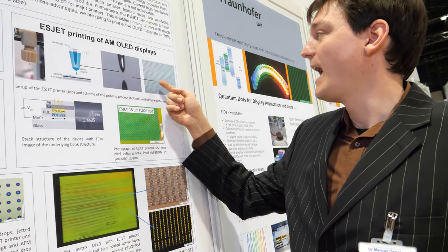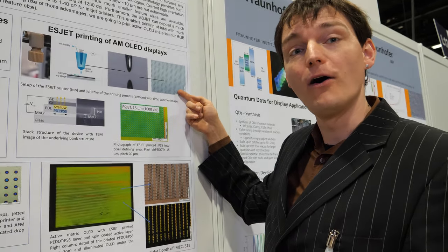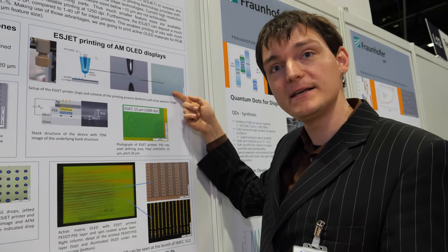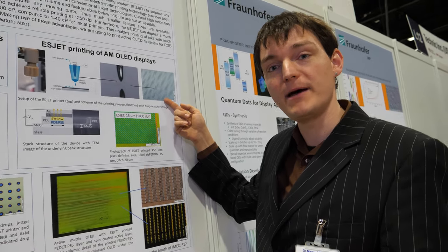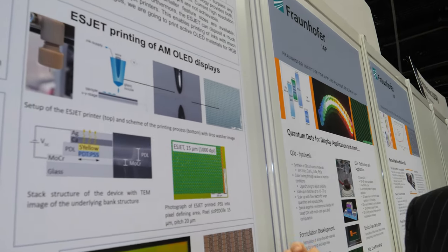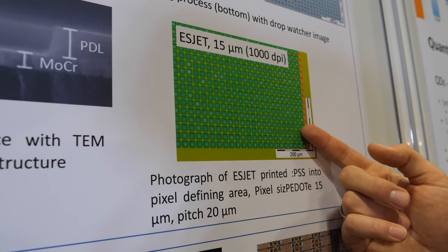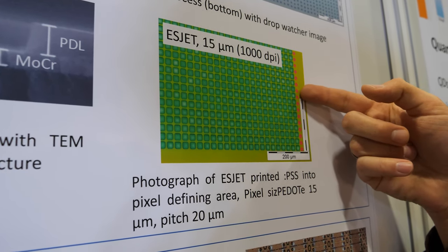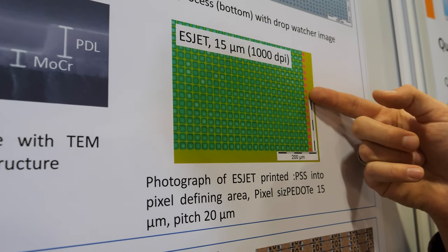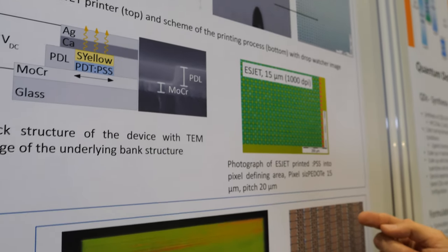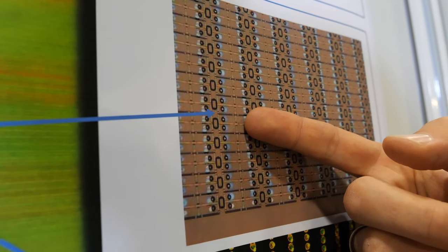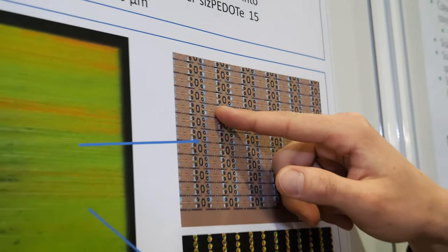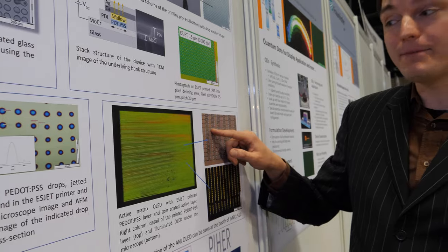And by this achieving high resolution printing of organic materials such as PEDOT:PSS, which is shown here with diameters of only 10 micrometer. And using this printing technology and printing them into well-defined cavities, here you see 15 micrometer cavities with the droplets which have diameters of 10 micrometers, we finally could print on the active matrix backplane of IMEC and TNO, the Holst Centre, which they provided to us, and we were filling the small white dots here of 10 micrometer diameter each by printing.